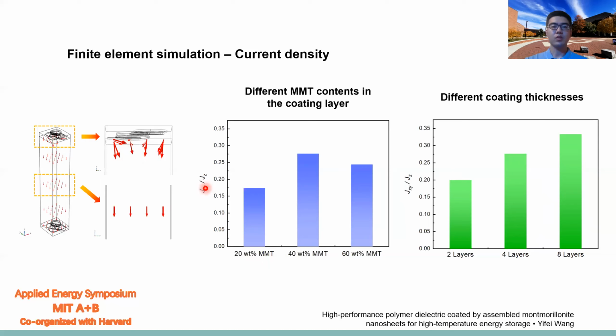And we checked the ratio of in-plane current density to the Z direction current. We find that these ratios can indicate how much current can be regulated to the in-plane direction. The sample with 40% MMT in the coating layer shows the highest value, which means that maybe this optimized MMT content gives rise to the highest regulating effect of the coating layer. We also checked this ratio in the coated polymers with different coating thickness. We can find that if we increase the coating thickness, these values are gradually enhanced, which means that maybe we need a thicker coating layer to get better performance.